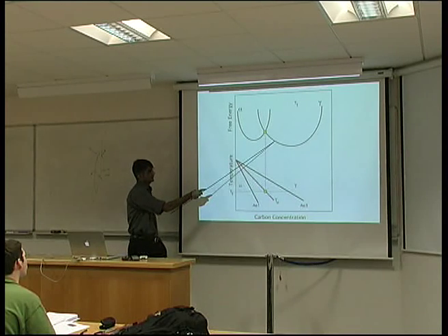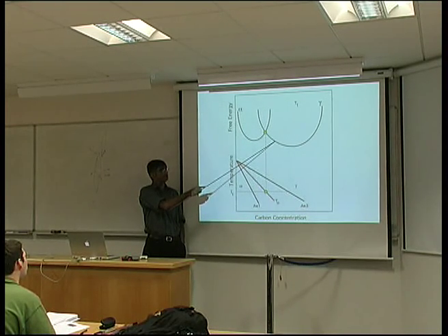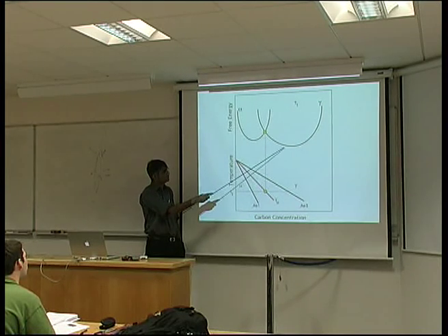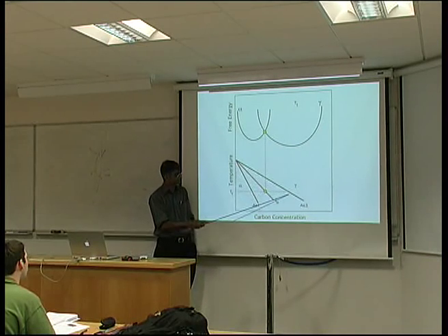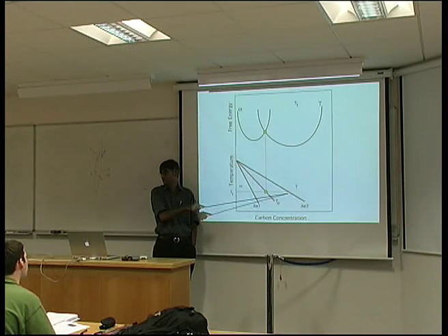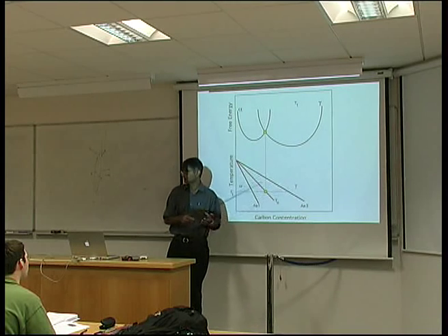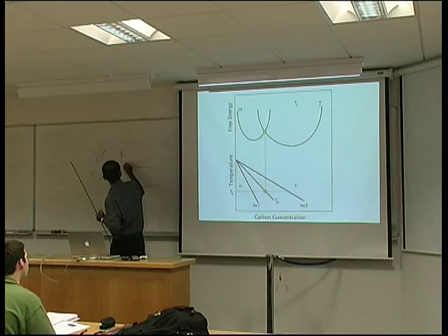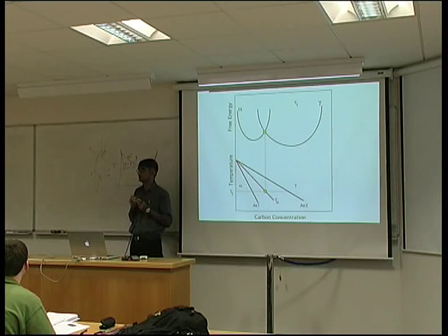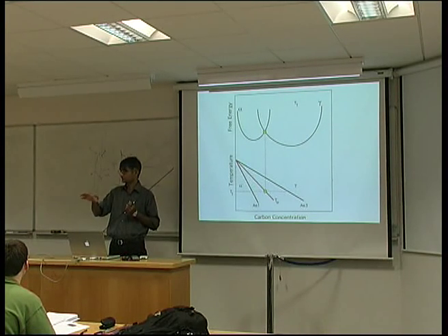Of course, I can transform it into an equilibrium mixture of ferrite and austenite. So if I take that common tangent, these are the equilibrium compositions. If I decompose it into a mixture of ferrite and austenite of those compositions, I do have a reduction in free energy. So equilibrium transformation can happen if my austenite composition is less than the AE3 phase boundary, which is the boundary between the alpha plus gamma and gamma phase group. On your iron carbon phase diagram, temperature, carbon, the diagram looks something like this, doesn't it? And this is alpha plus gamma and gamma, and this is called the AE3 curve. That's just jargon. It's basically the phase boundary between the austenite and the austenite plus ferrite phase group.